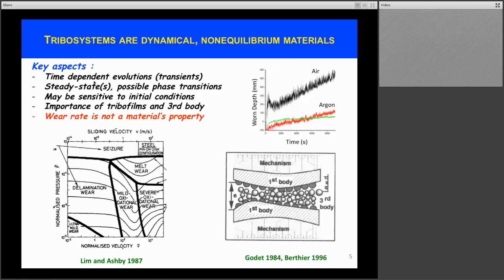First, we'll see time-dependent evolutions with transients. So for instance, here on the right-hand side, you have a wear depth as a function of time for a particular pin-on-disk wear test. And you see on the black curve that there's an initial transient that may last for here about 15, 20 minutes. And after that time, the wear depth increases linearly with time. So we have reached a steady state.